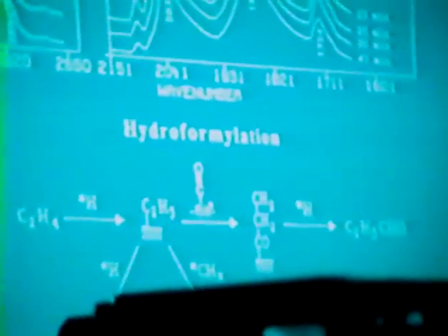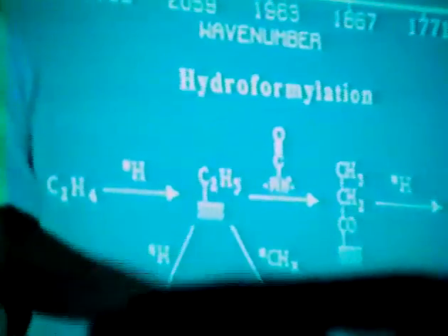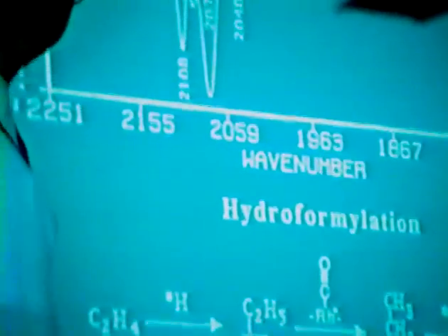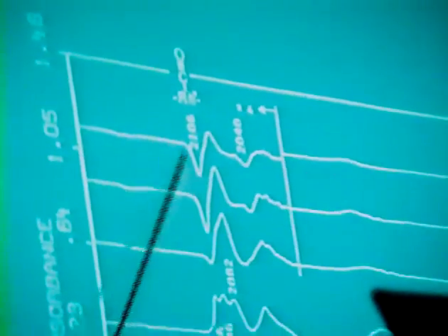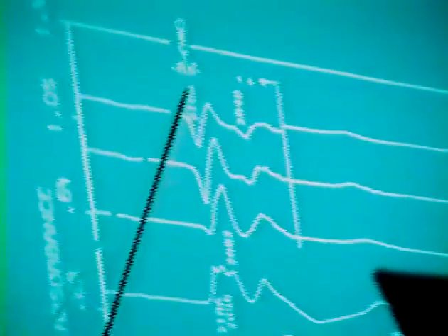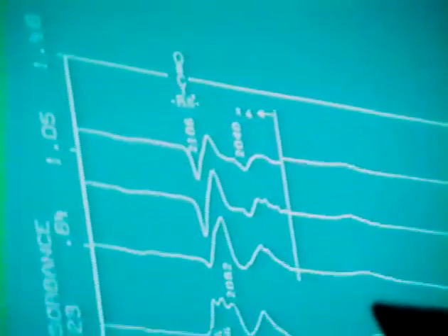Next please. Okay, a similar study has also been performed on the oxidized rhodium catalyst, and that result has been presented in Budapest, so I just want to quickly summarize here. This is a difference spectrum. From the difference spectrum, we conclude the species which exhibits the band at 2106 is responsible for the formation of the aldehyde species.